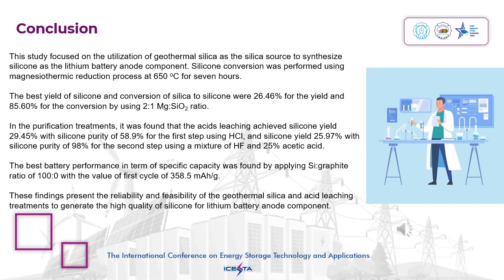The study focused on the utilization of geothermal silica as the silica source to synthesize silicon as the lithium battery anode component. Silicon conversion was performed using the magnesiothermic reduction process at 650 degrees C for 7 hours. The best yield of silicon and conversion of silica to silicon were 26.46% for the yield and 85.6% for the conversion, using a 2:1 magnesium and silica ratio.